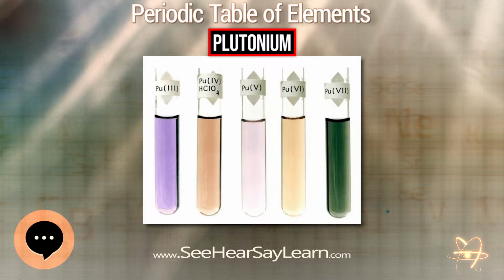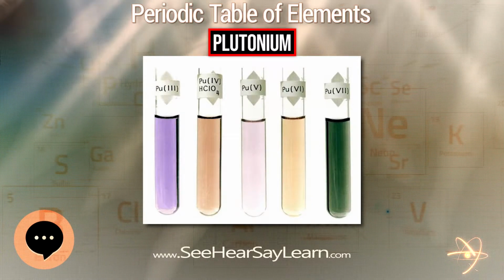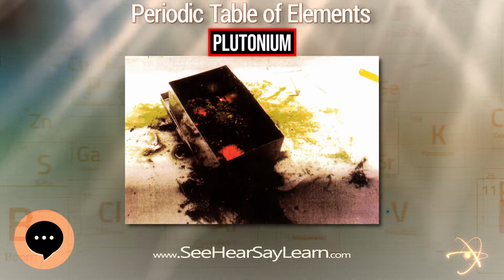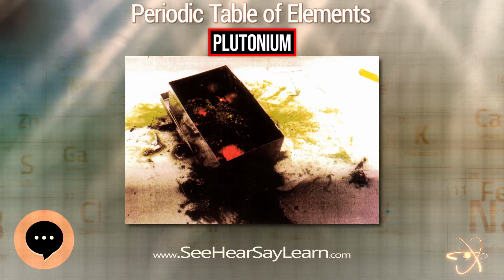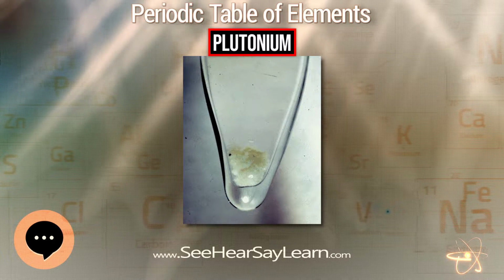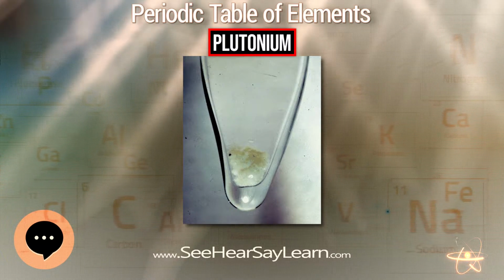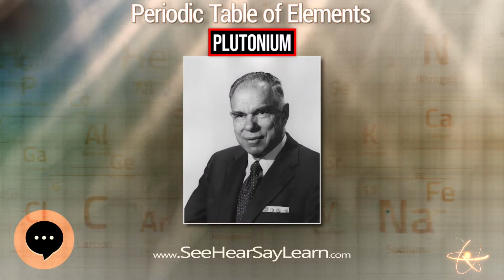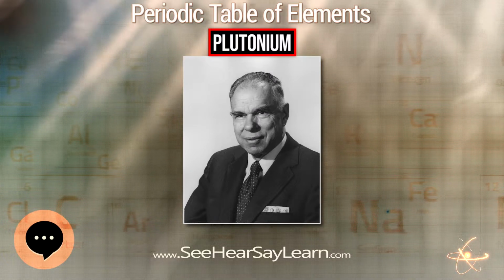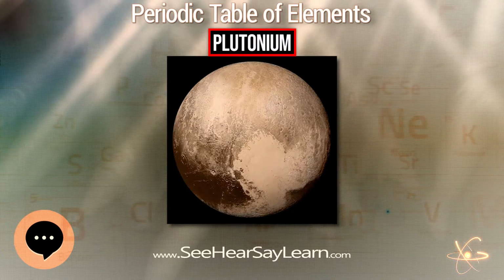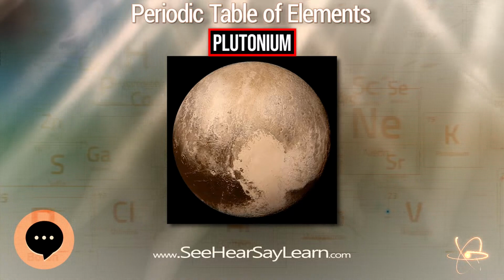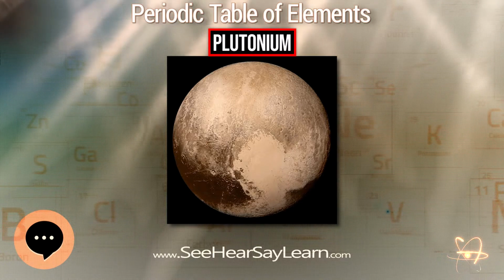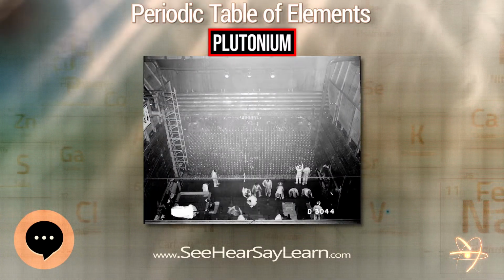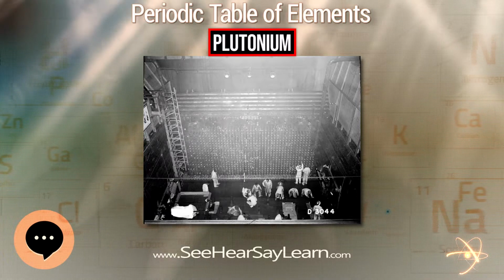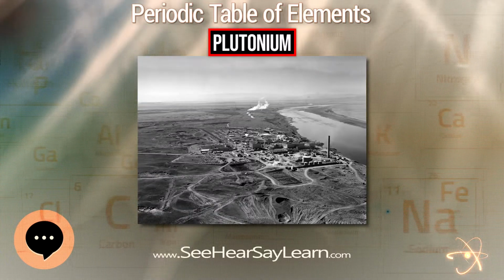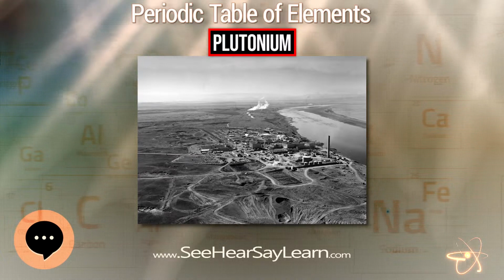Plutonium can form alloys and intermediate compounds with most other metals. Exceptions include lithium, sodium, potassium, rubidium, and cesium of the alkali metals, and magnesium, calcium, strontium, and barium of the alkaline earth metals, and europium and ytterbium of the rare earth metals. Partial exceptions include the refractory metals chromium, molybdenum, niobium, tantalum, and tungsten, which are soluble in liquid plutonium, but insoluble or only slightly soluble in solid plutonium.